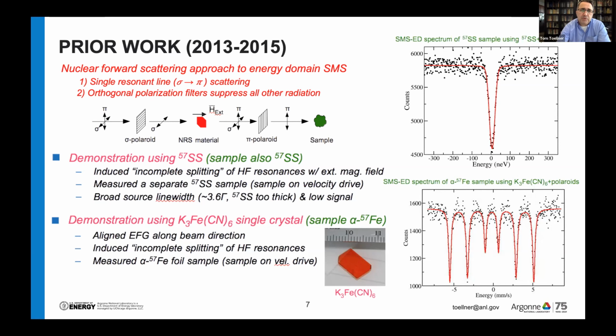So I did this, trying to generate a single line, and I used 2 different methods. One, just a magnetic interaction using stainless steel placed between cross polarization filters. Then I applied a small magnetic field. The stainless steel grade was a non-magnetic grade of stainless steel. But if you apply a small external magnetic field, you can introduce some partial splitting, and this allowed me to introduce some polarization flipping and generate a single line. So the spectrum on the upper right-hand corner is a measurement of another stainless steel foil as the sample. So the emitter is a stainless steel and the sample is a stainless steel, and I could scan one against the other and generate that Mössbauer absorption spectrum.